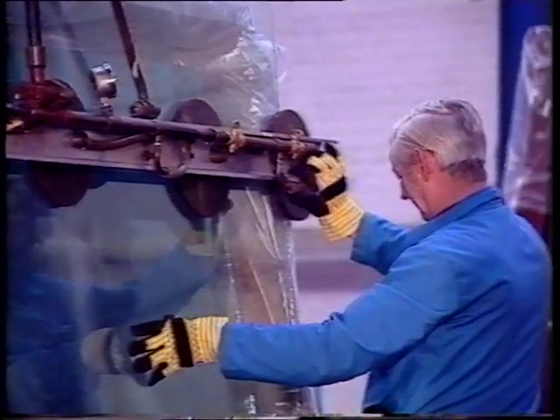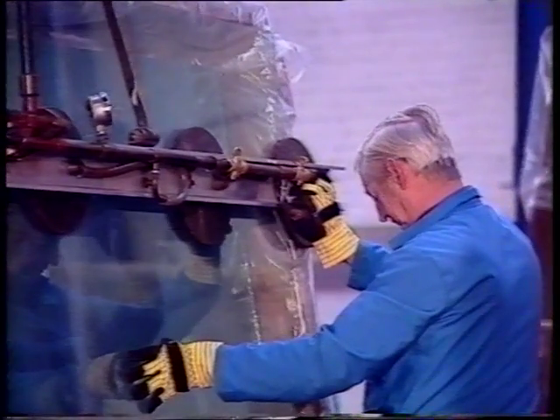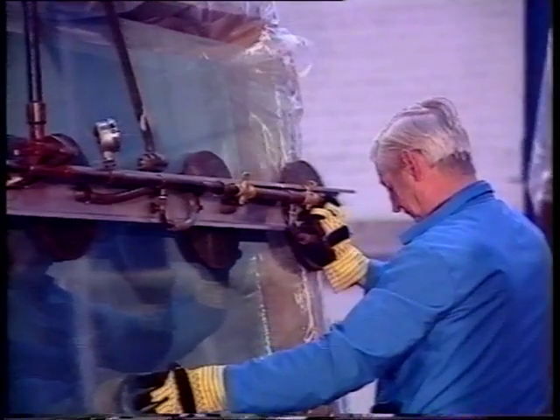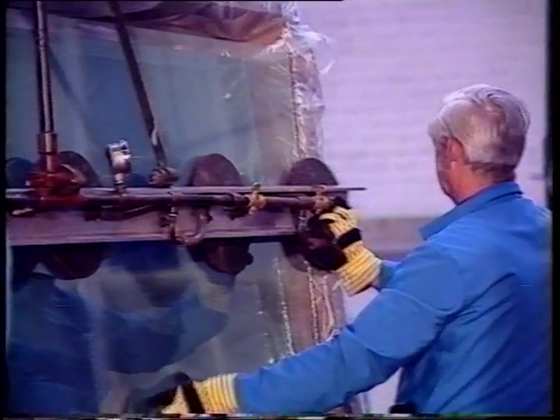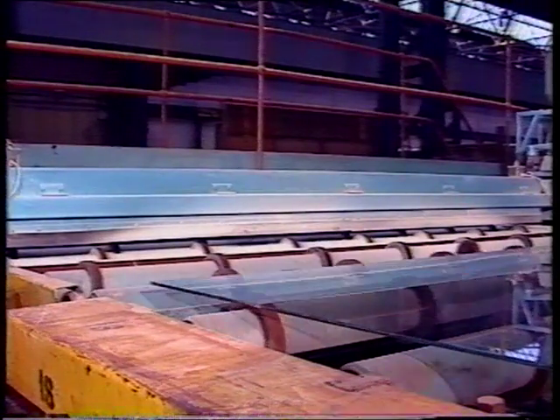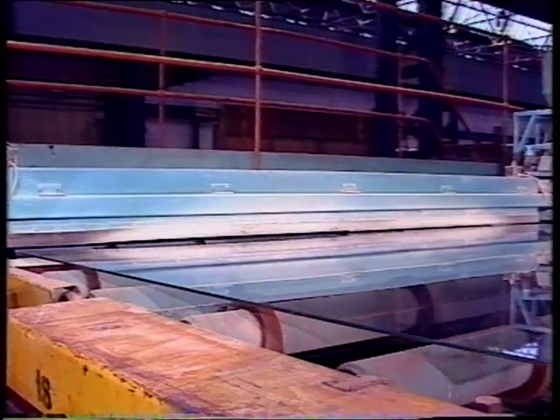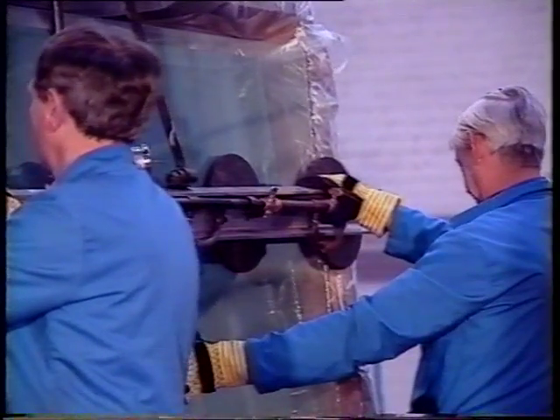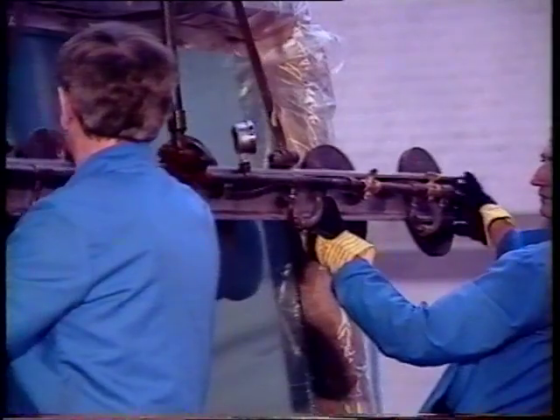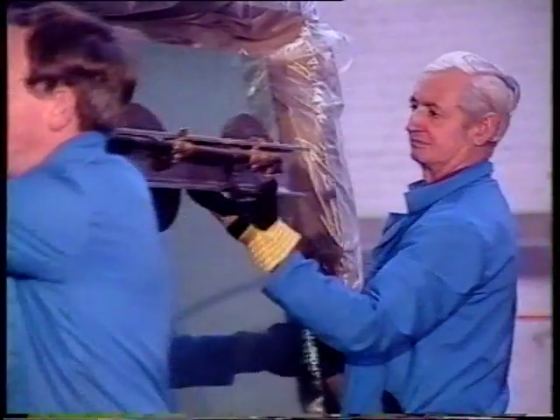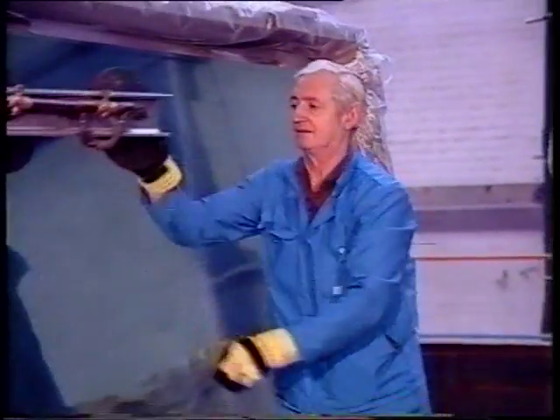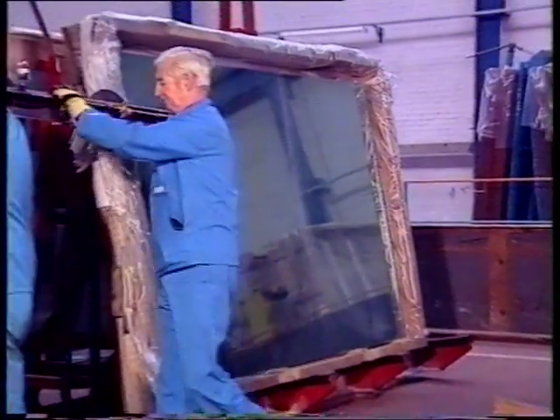Particular attention has to be paid to all glass loads to ensure that glass arrives at the customer in good condition. A good cover of lucite interleavant powder is applied to prevent scratching and rubbing during transit, and the glass is carefully packed to specified standards and targets. Any deviation from these targets can cause scars or breakage problems during transit.